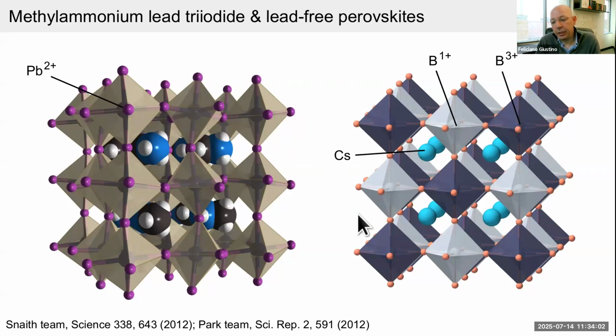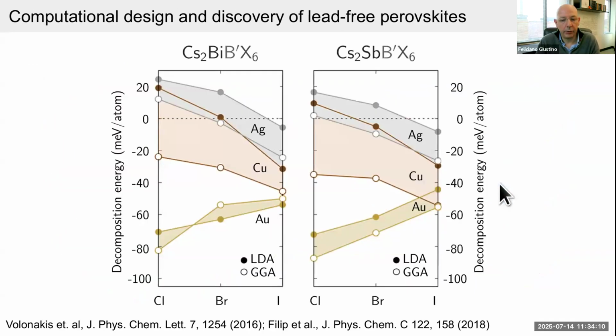And we performed a study of any possible combinations of these materials that you could form in this kind of stoichiometry. So this is just a summary of what we found. These diagrams show you basically the density functional theory decomposition energies of some of these compounds. And in particular, this is cesium-2, bismuth, B prime is a noble metal, and X is either chlorine, bromine, or iodine.